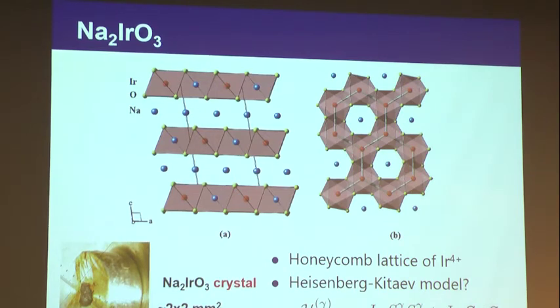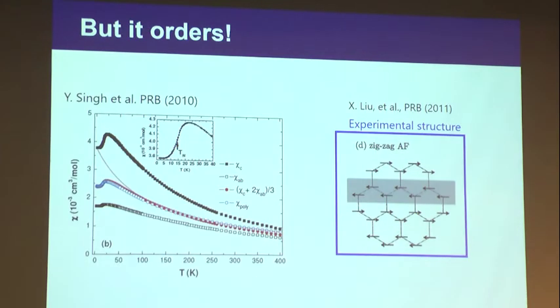So, okay, great. Is it a quantum spin liquid? Sadly, the answer is no, because it orders. Immediately after synthesizing this, they measured the magnetic susceptibility and saw a magnetic ordering happening around 15 Kelvin. Soon afterwards, John Hill's group at Brookhaven did resonant X-ray scattering work on this material, showing that the magnetic structure looks like this, a so-called zigzag antiferromagnetic ordering, where the spins along this honeycomb zigzag are all ferromagnetically ordered, and they are coupled antiferromagnetically between them.